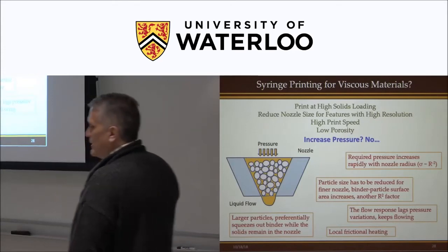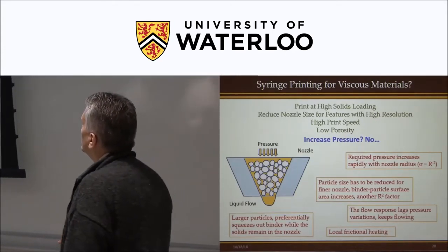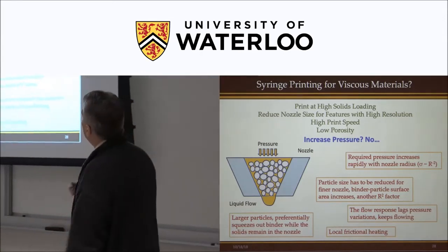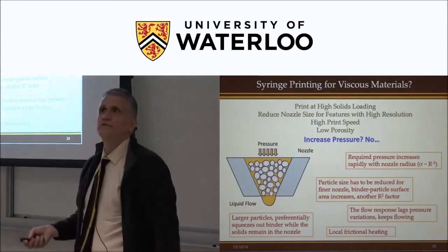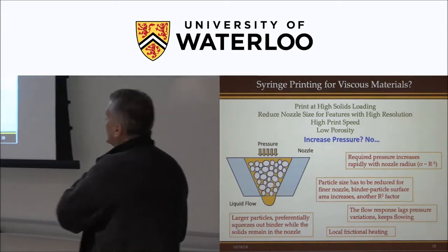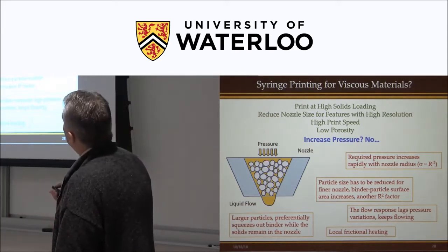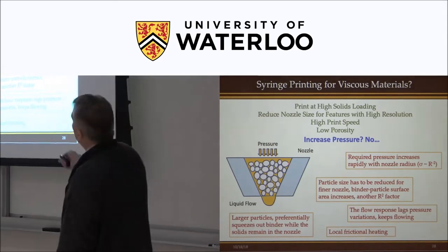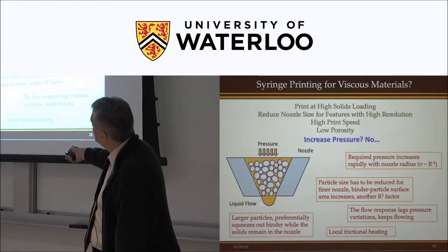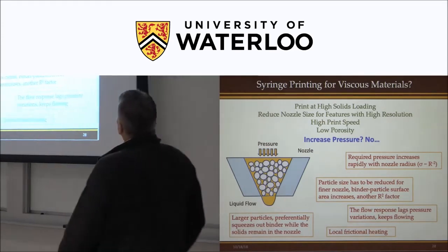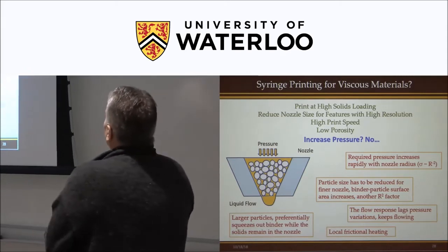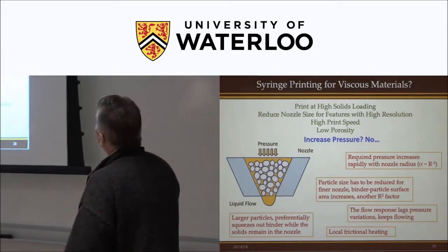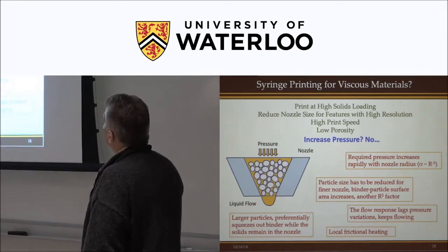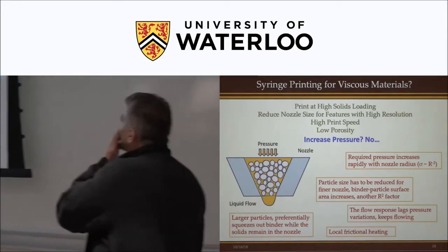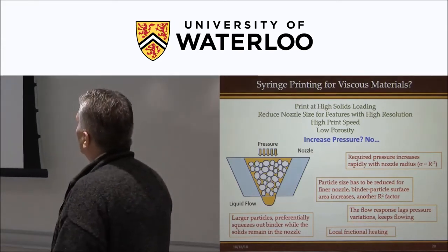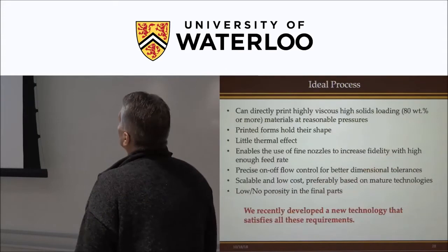So you would think, well, maybe if we're printing this viscous material with a nozzle, we'll just increase the pressure. But if we increase the pressure of a highly solid-loaded viscous material, those particles can bind together, and the pressure could succeed at extruding just the binder, so it de-wets. And that rapidly increases as you go to smaller and smaller nozzles. You have to have smaller particle sizes for finer nozzles, and there's local frictional heating, all sorts of problems.